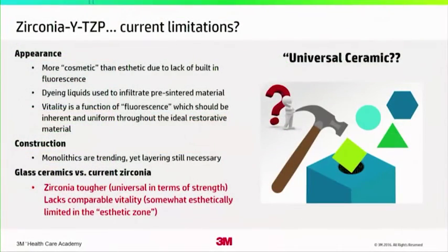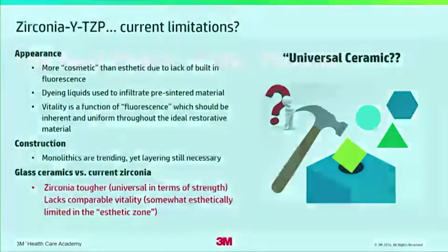So, when we talk about zirconia, we talk about, of course, this YTZP zirconia, the tetragonal zirconia. That's a hard thing to say sometimes, to get it all out in one time. But we know that the material actually works, and doctors like it. We have an understanding now why monolithic may be the way we want to go and what the reasons for that might be. The construction principle actually makes a lot of sense, but there are limitations. We know it's strong, and we know if it's handled properly, it'll perform, but it still seems to lack the vitality associated with restorations that we would like to do in the aesthetic zone, particularly as it applies to the idea that we would like to do potentially monolithic zirconia and eliminate the layering effect.